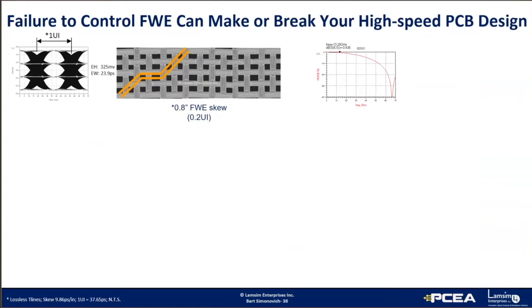0.2 UI of skew will cause a resonant null in the insertion loss plot at 5 times the Nyquist frequency of the baud rate. In this case, the Nyquist frequency is 13.28 gigahertz, and the resonant null is at about 66 gigahertz. We also note approximately 0.4 dB loss at 13.28 gigahertz. And at the far end, the eye shows we lose about 3 millivolts of eye height and about 1.5 picoseconds increase in jitter.